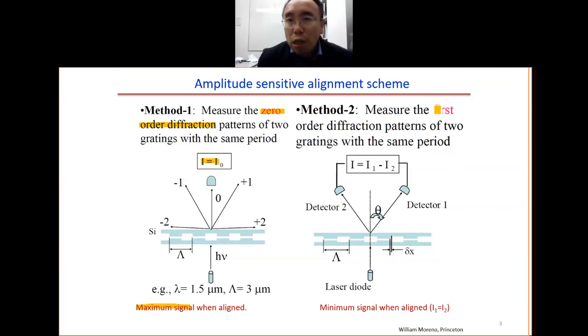We can also do the first order alignment. When we do the first order diffraction, you have the laser light coming in, you get one diffraction to the left, one diffraction to the right. So you measure the distance. When they are symmetric, when they are well aligned, you get the minimum signal, zero signal. That's one way to do the alignment. We use gratings. The relative position of the two gratings tells you the misalignment.